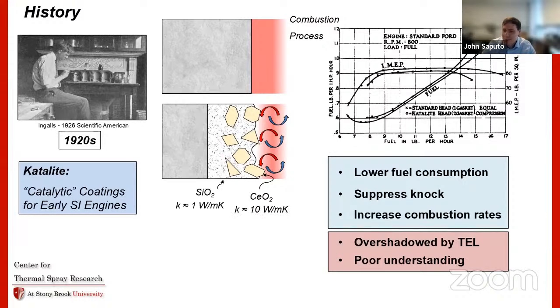And there's an interesting aspect of this, whereas you have a silica coating on the surface, which has a conductivity of maybe on the order of something like 1 watt per meter Kelvin, versus the steel or aluminum that it would have been made out of, that'd be 40 to 100 watts per meter Kelvin.